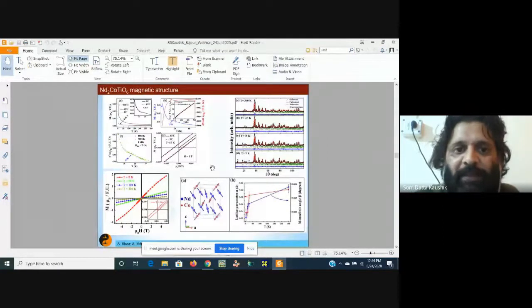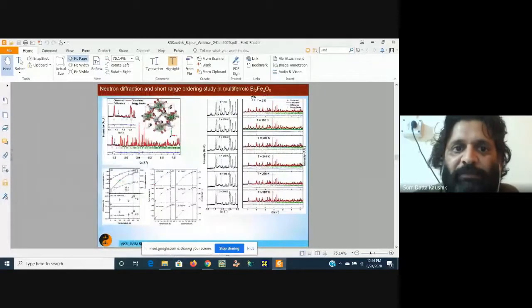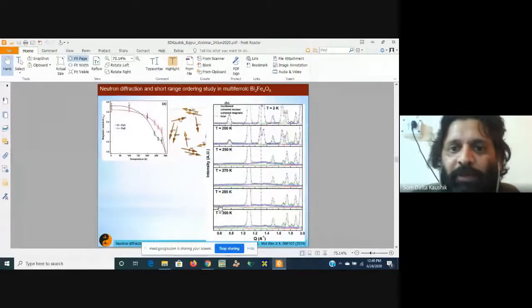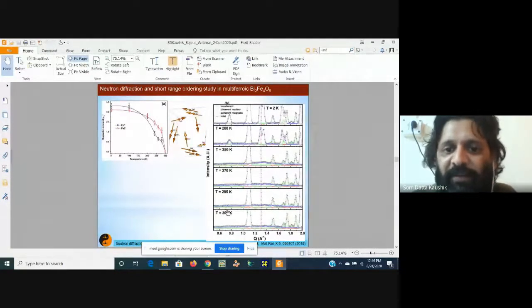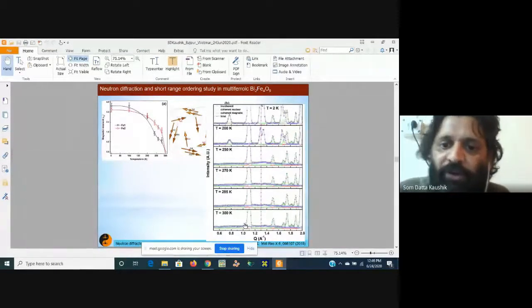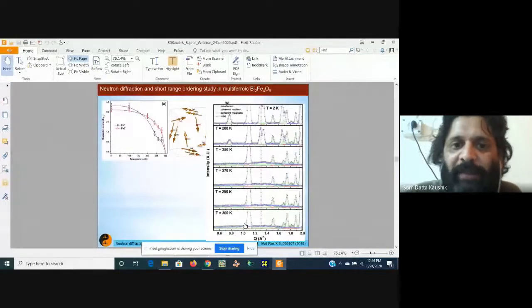Another example is Bi2Fe4O9, in which there was an indication of short range ordering at room temperature. But when we carried out low temperature neutron diffraction, we could see the short range ordering converting into long range ordering. To understand whether the short range ordering is magnetic or non-magnetic in nature, we carried out polarized neutron diffraction at low temperature, on a different instrument, not this one. We can see that the short range ordering at room temperature is magnetic in nature.